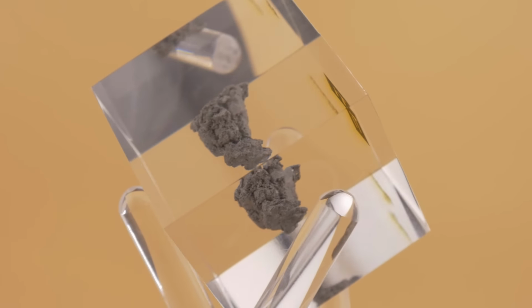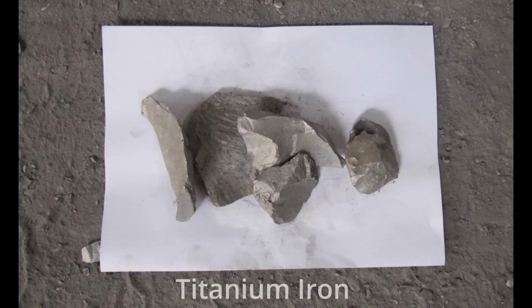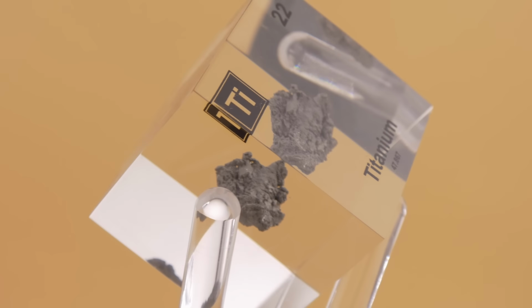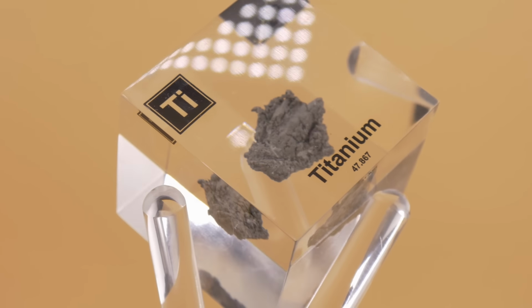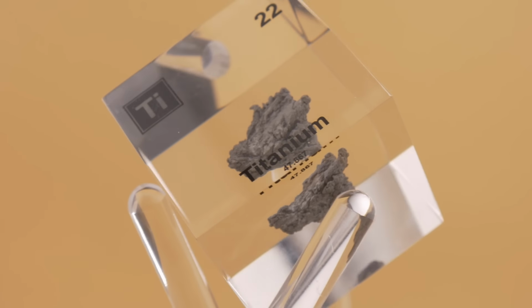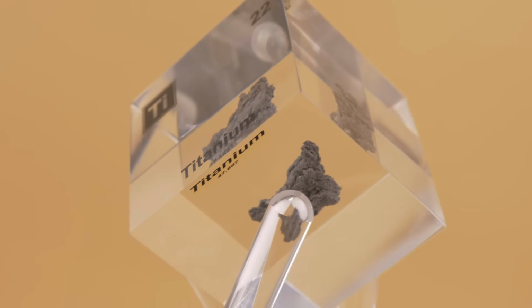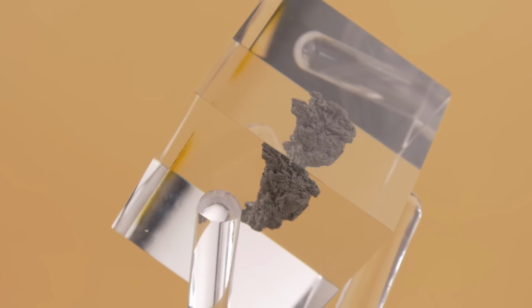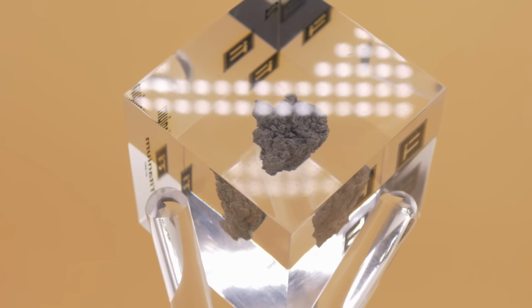Some are troublesome, like iron. If you weld titanium to steel improperly, you can form brittle titanium iron intermetallics that cause cracks. Others are currently being researched, like titanium silicides or titanium with certain rare earths for special electrical applications. But in terms of broad significance, the big two are covered: titanium aluminides and nitinol.